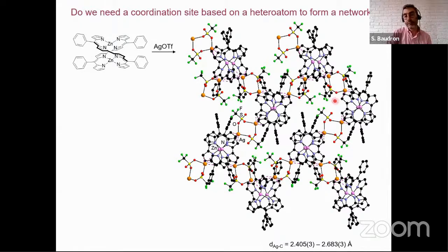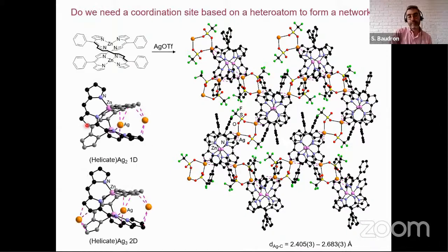By playing with the solvent conditions, we were also able to obtain a two-dimensional network, in this case not with two silver cations per helicate, but actually three cations per helicate, giving this two-dimensional architecture. So you can see here how this is organized for the 1D case and how this is organized for the 2D case. We have also obtained a two-dimensional network with four silver cations per helicate, playing with silver perchlorate in this case.